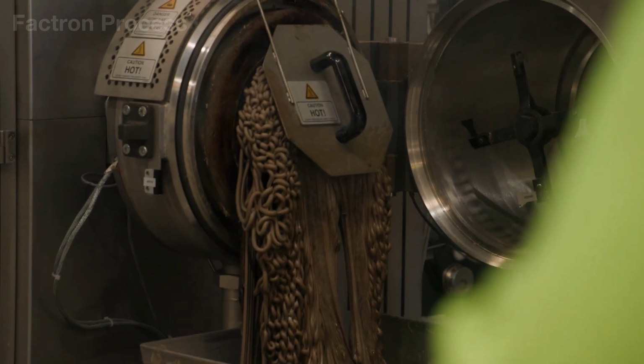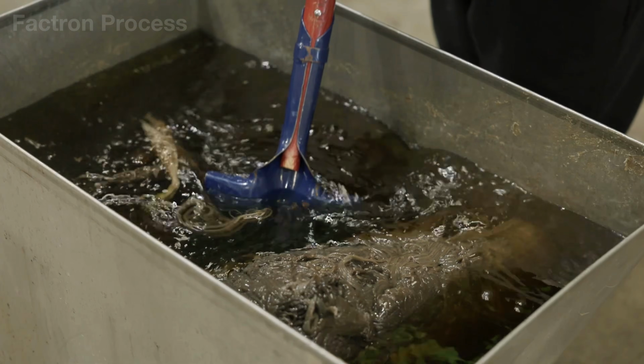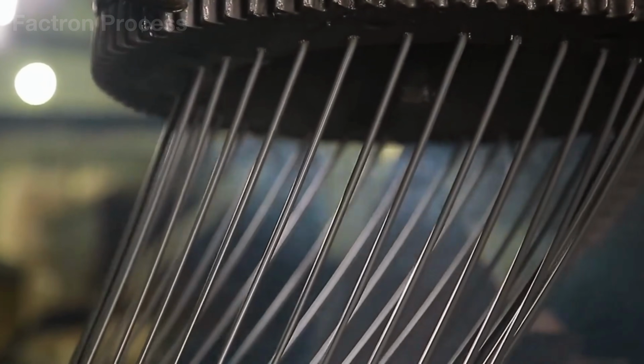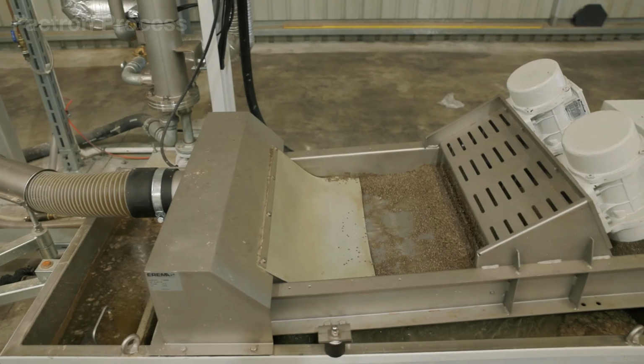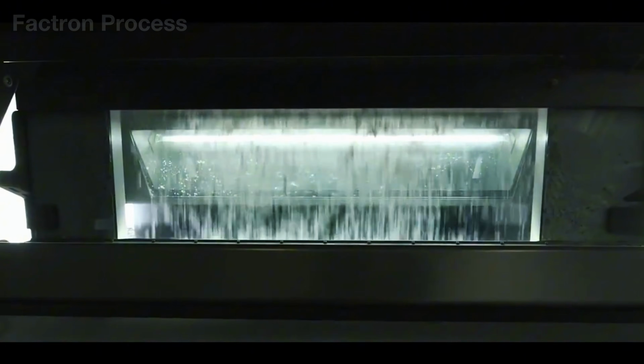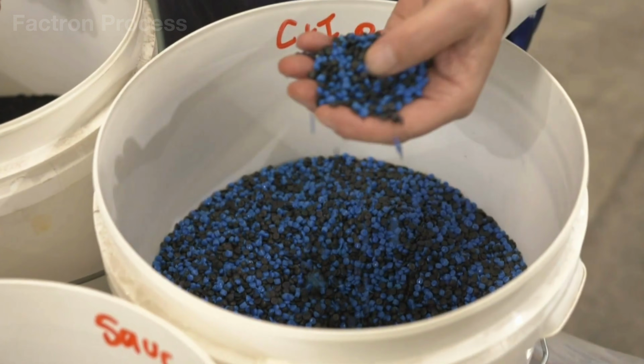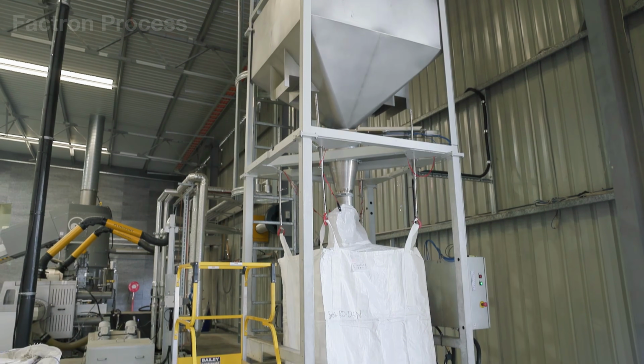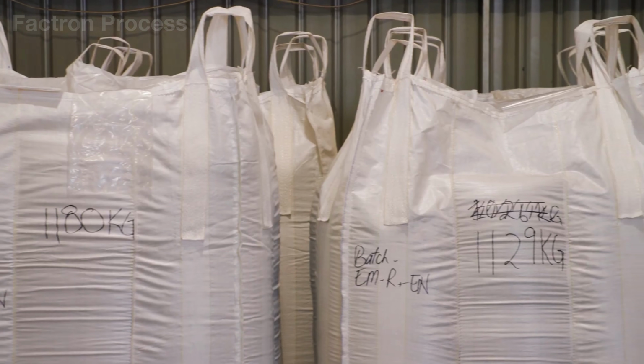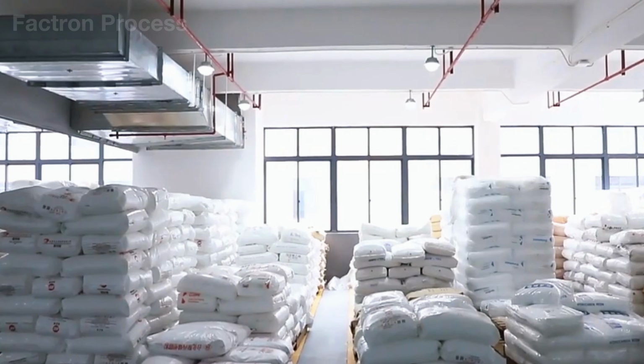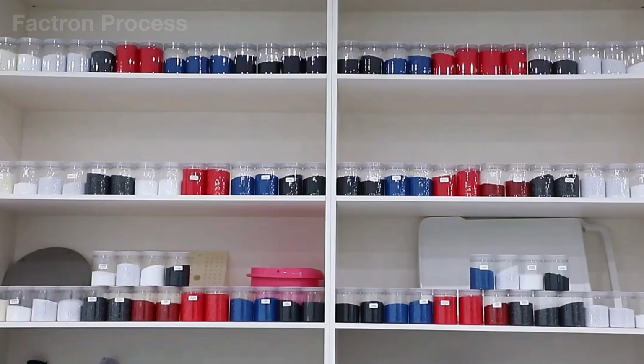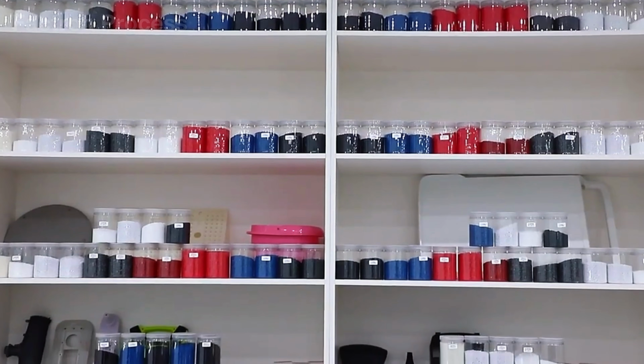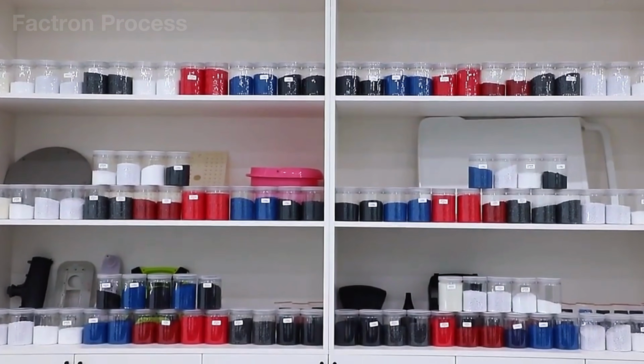The molten plastic is extruded into thin strands, rapidly cooled in water, and then fed into a high-speed rotary cutter. In an instant, hundreds of sharp blades continuously slice the strands into millions of tiny PP pellets, each about the size of a grain of rice. At this facility alone, the recycling process produces around 20 tons of recycled PP pellets every day, providing a stable raw material supply for the synthetic rope manufacturing process.